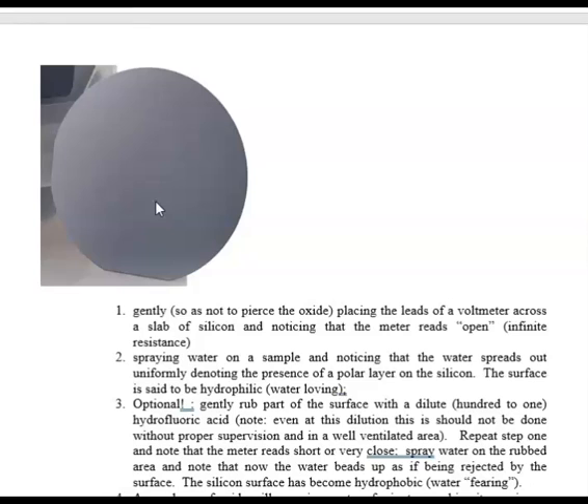Silicon dioxide is an insulator, so because we get an open reading, there is something on the silicon which basically insulates it. There's another way to show that we do have an oxide layer on the silicon, and that's by spraying water. You'll notice if you do that on a silicon wafer, and I've done this many times in class, the water will spread out over the silicon because glass is hydrophilic. So that's another way to show that there is indeed an oxide layer on the silicon.